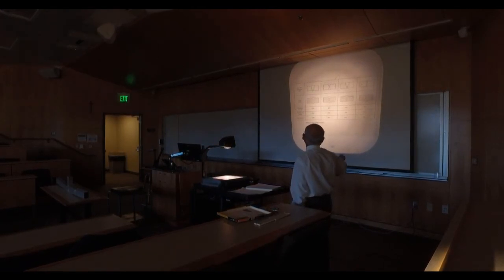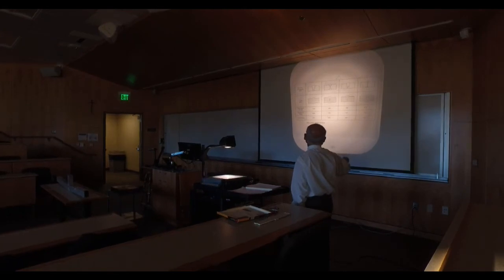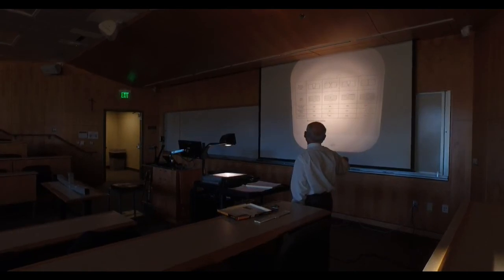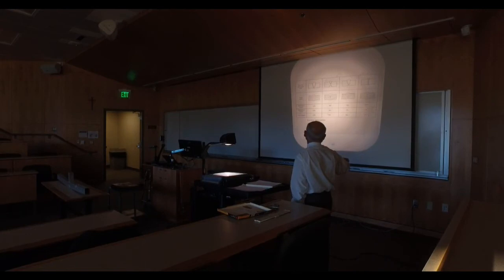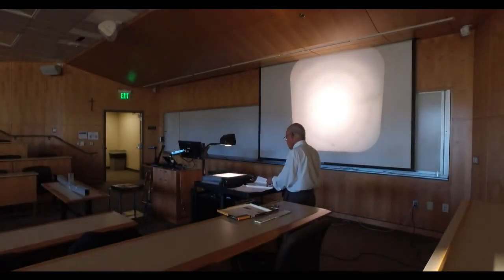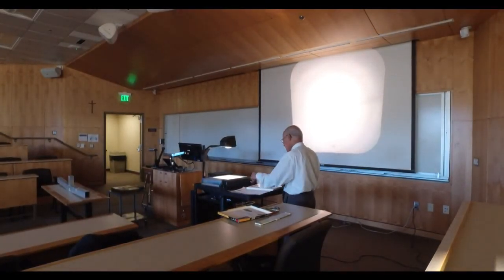You don't want any notches where there's fatigue involved, fatigue loading. And again, this one is probably the worst. You can see there's a big, huge discontinuity. This is 60% of static tensile strength, 40% loss. This is 90% loss. And this is 60% loss in toughness. So the point is, discontinuities are bad. And I think you already knew that, because you all come from a welding background.